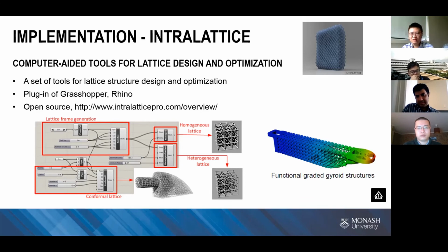But practically speaking, if we go to industry use, there are some issues. One issue is that if you pass the coolant, and especially if there are small particles inside the coolant, the small particles will hit the lattice structure. It's not circular or very smooth, because even though you fabricate the lattice structure by additive manufacturing, the particles will hit the structure, and it may break. Also, the lattice structure is under a certain load, and maybe will make the mold crack.